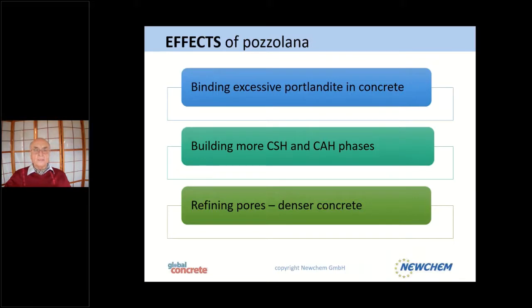So what are the effects? We bind the excess portlandite, or calcium hydroxide, in the concrete. By this, we build more calcium silicate hydrate or calcium aluminate hydrate phases. We refine the pores. We have heard today that water ingress is detrimental, and normally, with chlorine, the migration of the chlorine is also increased. So refining the pores means less water transport, less chloride transport, and a denser concrete.